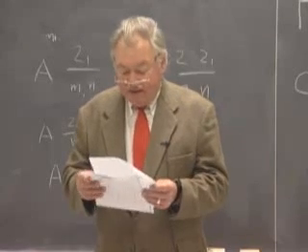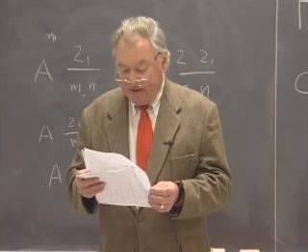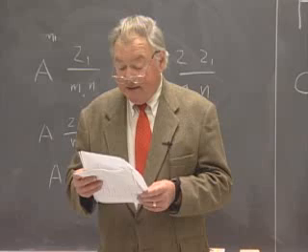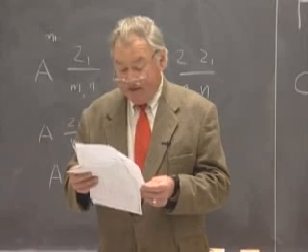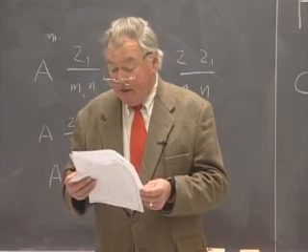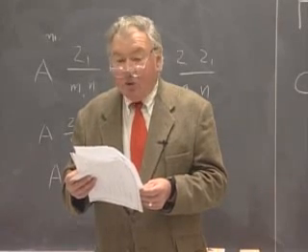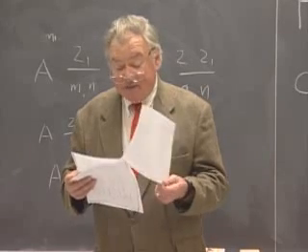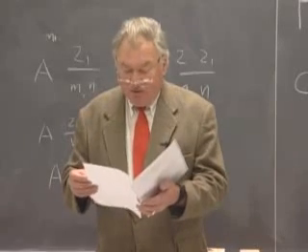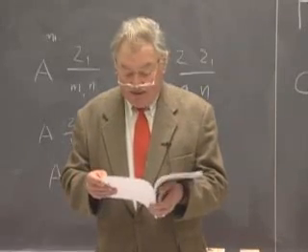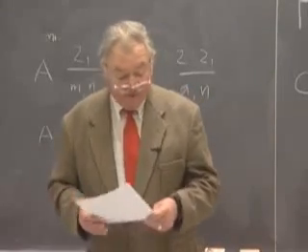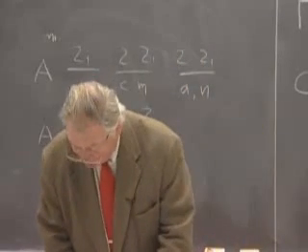And then finally, cubic, a fair number of cubic symmetries, but the edge of the cell is always along the direction of the 4-fold axis or the 2-fold axis, depending on whether the symmetry is based on 2-3 or 4-3-2. So there are really no alternative symbols for different settings of the symmetry elements relative to the edges. So there you have them, all 230 of our cast of characters, but in the very different mantles in which they can be cloaked.